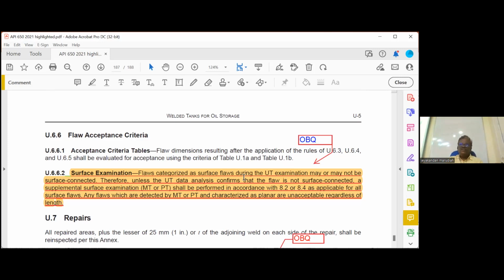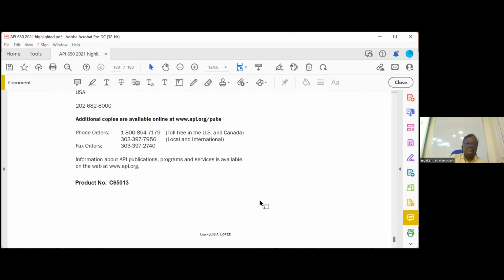Flaws categorized as surface flaws during UT examination may or may not be surface connected. Therefore, unless the UT data analysis confirms that the flaw is not surface connected, a supplemental surface examination, MT or PT, shall be performed for all surface flaws. Any flaws which are detected by MT or PT and characterized as planar are unacceptable regardless of the length. So if MT or PT shows some linear indication, you have to repair it. Okay, that's all for API 650.